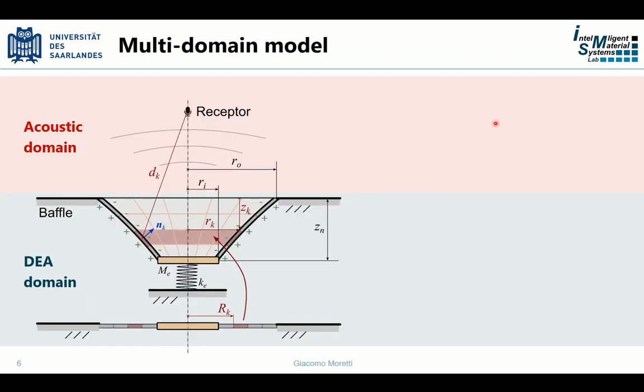We built a model for the cone DE loudspeaker, combining a model of the structural dynamics of the dielectric elastomer actuator domain and a model of the acoustic domain. In this presentation we just look into axial symmetric deformations of the DE membrane and symmetrical acoustic fields. Although this might seem a strong simplification, in fact, the axial symmetric deformations of the membrane are expected to account for most of the radiated sound pressure.